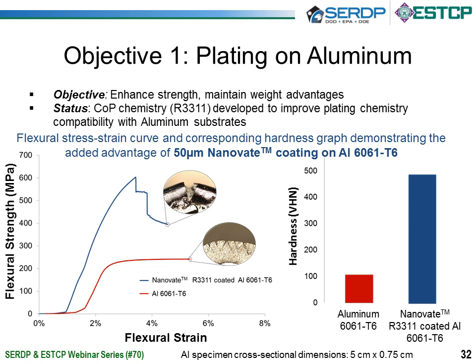So the second part of Objective 1 was to see if we can tweak the process in order to more readily coat on aluminum. In the past, we have been able to use the standard process to coat on aluminum. However, the high temperature of the process as well as the lower pH did result in some concerns with coating onto aluminum, since the solution was fairly aggressive if any aluminum was exposed while you're coating. So if you're fully encapsulating and putting a part in, coating all surfaces, it's no problem.